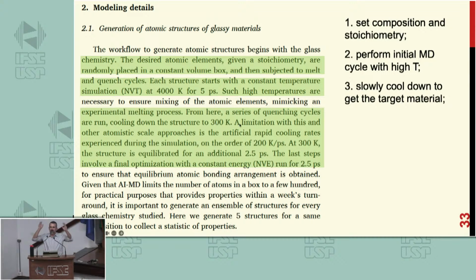So you have something that is random there, atoms randomly distributed. So you start decreasing the temperature until you get a structure that you can simulate. And they want to cool down from 4,000 Kelvin to 300 Kelvin. And here comes one thing that Hino said, and Zanotto also said, that is the different time scales of simulations and experiments. So look here. The cooling rate was 200 Kelvin per picosecond.